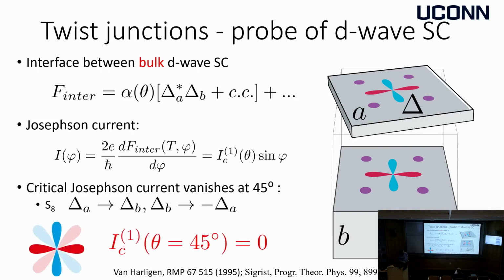And the statement specifically allowing you to determine that your superconductor is D-wave is the following. Let's consider this rotation angle to be 45 degrees. Then when I look from the top, the two order parameters are rotated like this. But also, if I look at my system, there's a new symmetry emerging. I can basically rotate the two layers by 45 degrees and then make an inversion. This is the so-called roto-inversion symmetry, which happens precisely at 45 degrees.